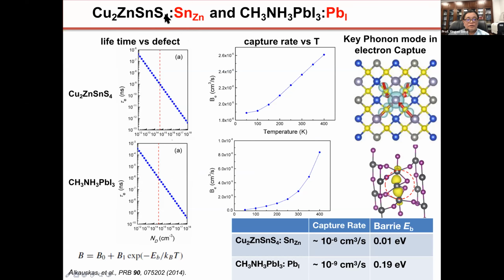quaternary semiconductors, we know this defect, zinc is replaced by tin. This defect is a bad defect. It really kills these electron holes, which will decrease the efficiency of the solar cell. And there is another most famous system, like ABX3. These systems have recently become very popular in solar cells. But we know these defects, where iodine is replaced by lead. These defects also kill these electron holes. And everybody knows that this one has very high efficiency. One can easily get more than 20% efficiency.